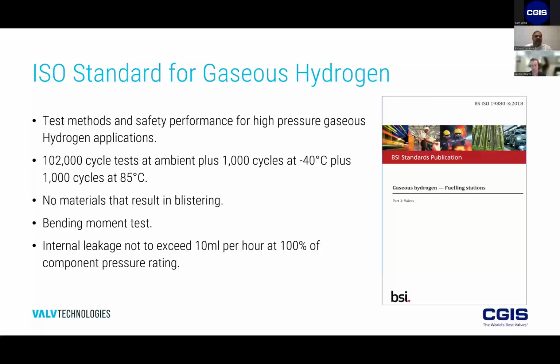But the intent here is that if a valve can pass these tests, then there should be no materials that result in any blistering. So again, it goes against rubber components that could be in there. The other thing that this standard, the ISO 19880-3, talks about is a bending moment test, which is somewhat unusual. Here any manufacturer has to prove that if a moment was applied to the valve itself, it can take that additional load. In reality, for most of the hydrogen systems that I've seen thus far, probably not too much of an issue.